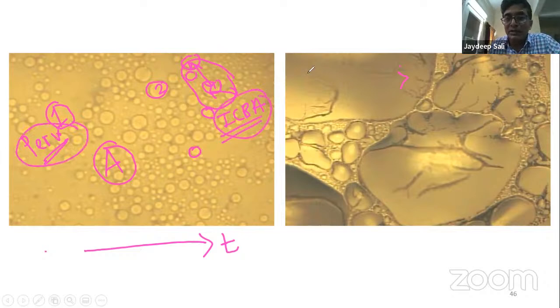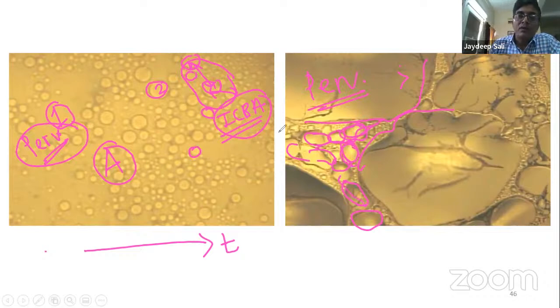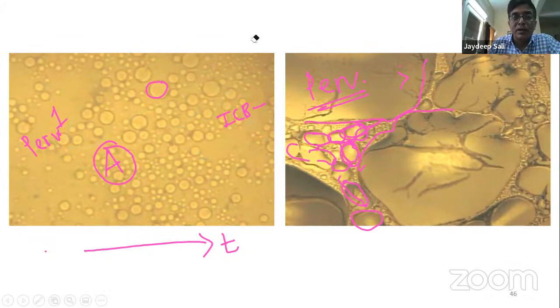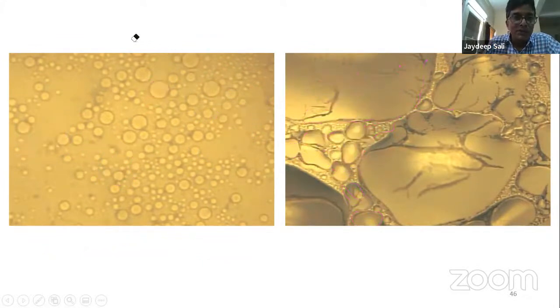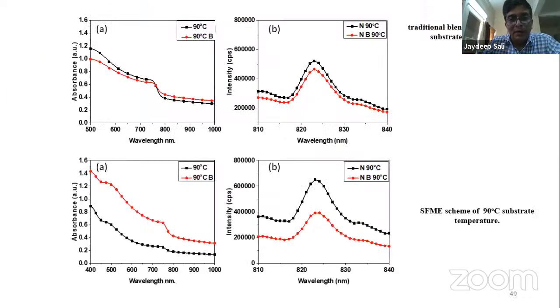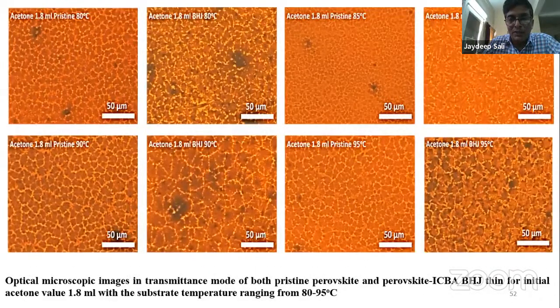So you can see here, you can say this is the perovskite crystals. These are the grain boundaries. And in the grain boundaries, you can form small crystallites of the second component, ICBA. In what way they are distributed here, with what size they are distributed, we can control by simulating the evaporation dynamics of the microemulsion, as we have seen. So this is how we are trying to fabricate thin films of perovskite as a photoactive layer.